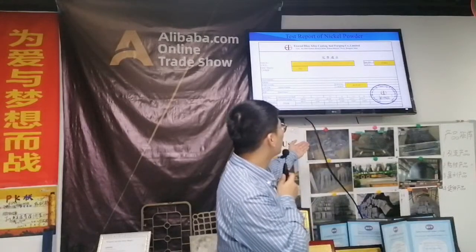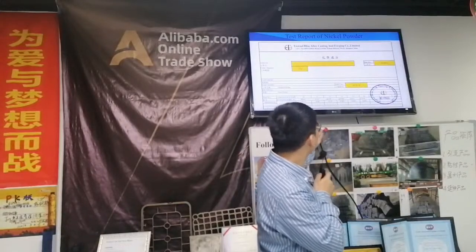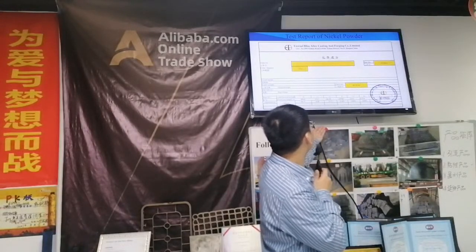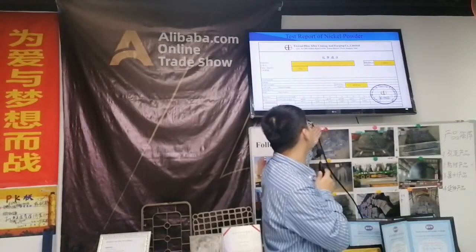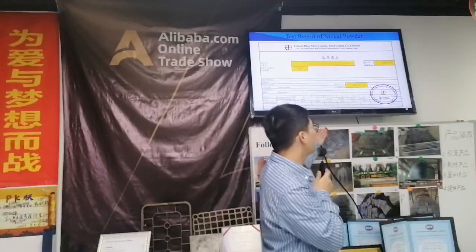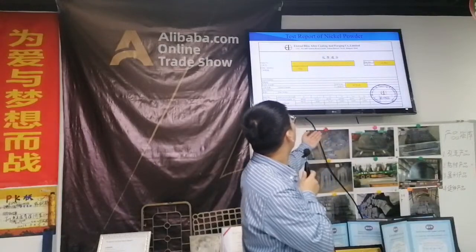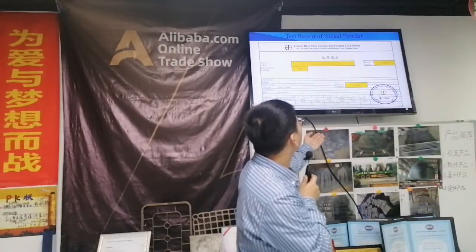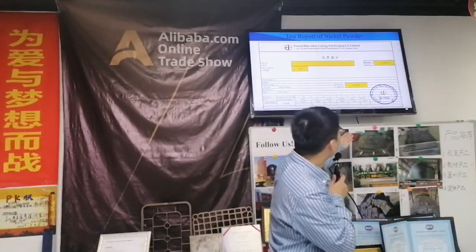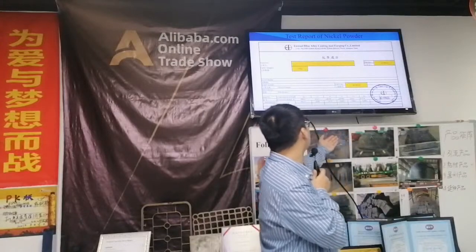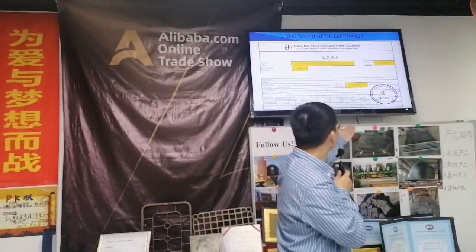And for the other elements, for example, the carbon, after we test, takes about 0.09, and the cobalt, which we need less than 0.01, is in fact 0.001.